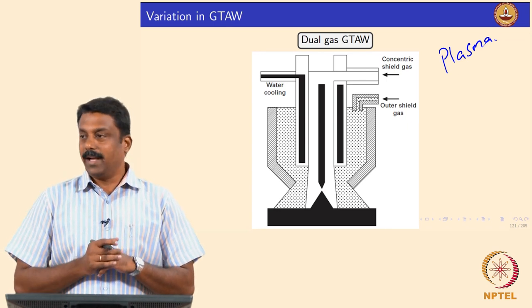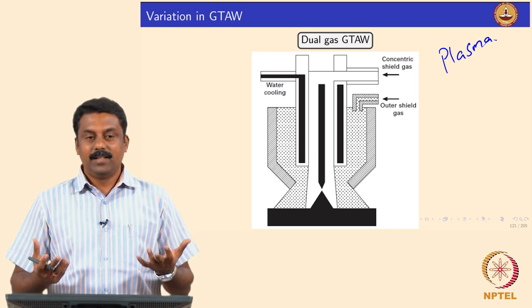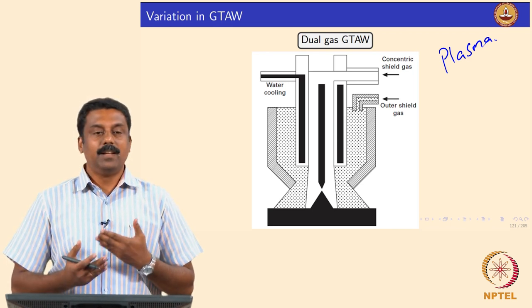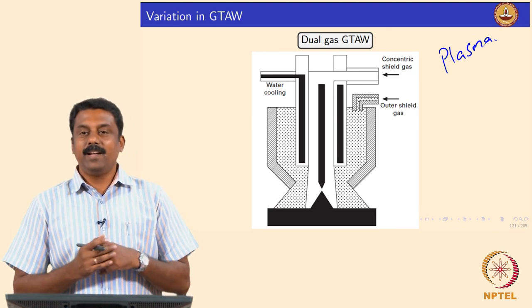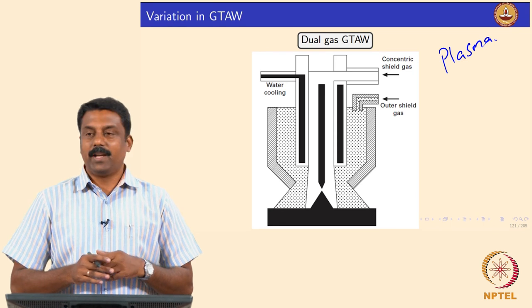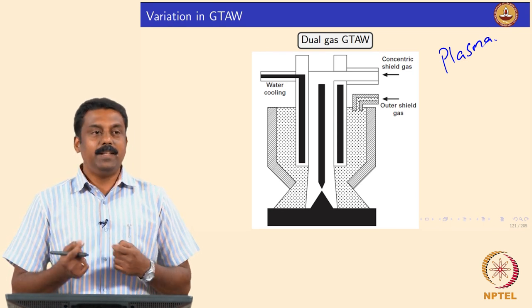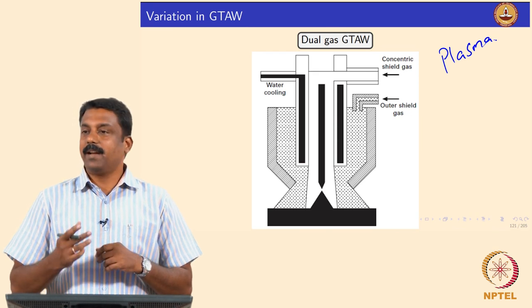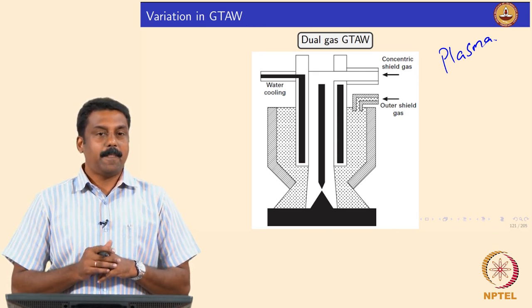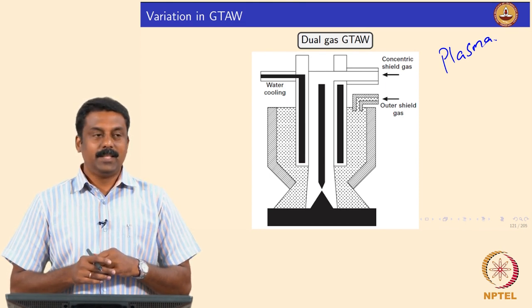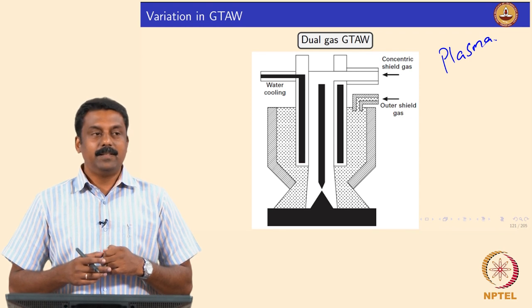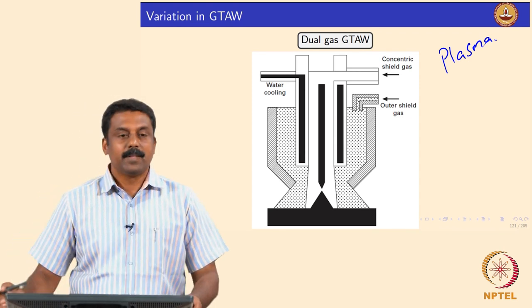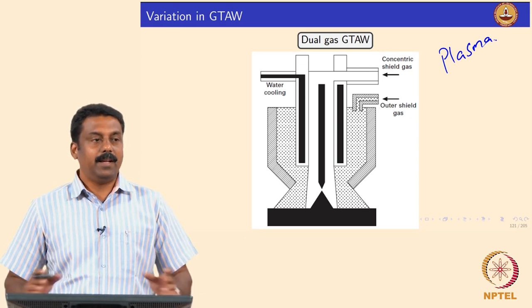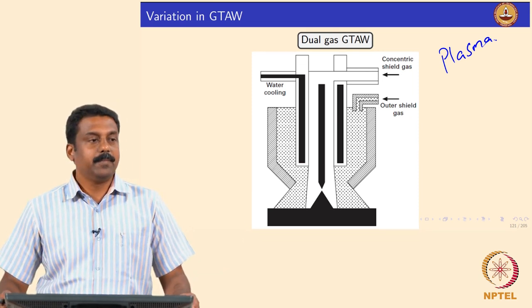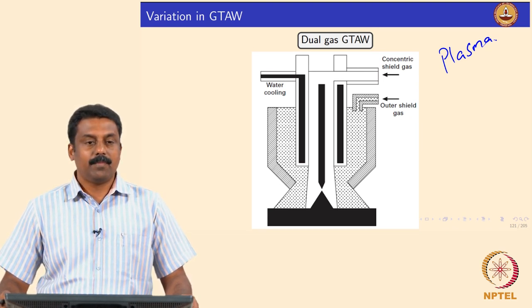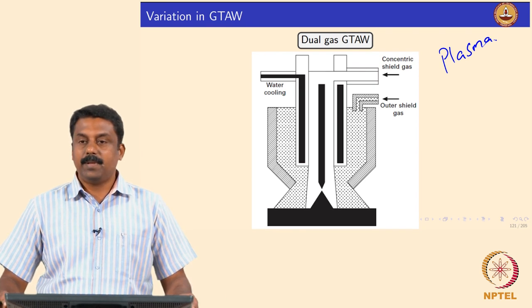Again, the heat transfer in arc is carried out in three ways, right? What ways? Conduction, convection, and radiation. Conduction and radiation, we cannot modify anything, but we can manipulate the convective heat transfer. What are the two mechanisms by which convective heat transfer takes place? Buoyancy and plasma jet formation. How do you define buoyancy? Density difference. At the middle of the arc we have a higher temperature, whereas in the arc envelope we have low temperature, and because of that we have a flow.